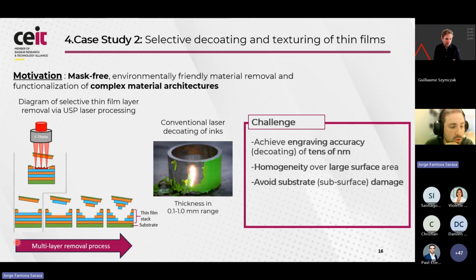So this is the diagram to show you a little bit what we mean by this. Essentially, when we're working with multi-layer stacks, we're able to selectively decoat or ablate the different layers and in different patterns. And depending on the use case, instead of decoating, you might want to texture the actual layer without affecting the ones that are below. And you can also achieve this with this technology. The challenge here is basically to have a high enough engraving accuracy, in the order of tens of nanometers, and also to have it be homogeneous across the whole surface area and not have any damage to the layers that are below.